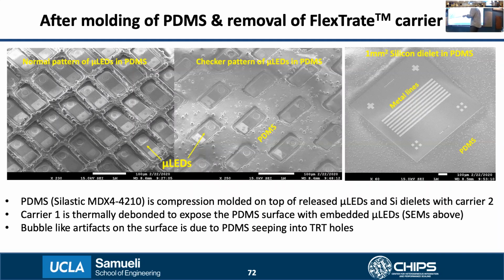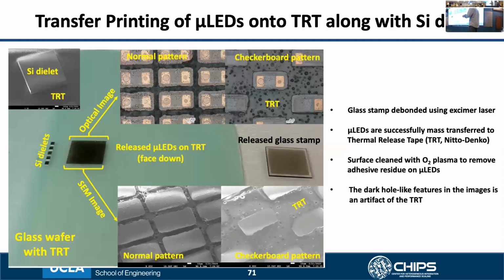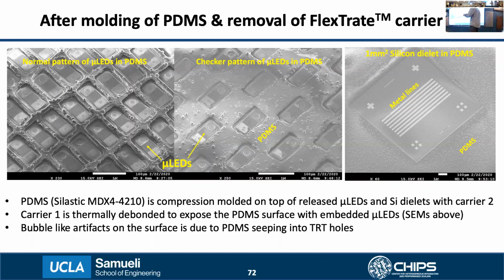So these bubble-like features that you see on the surface are actually an artifact of the thermal release tape, because the thermal release tape, if you notice here, has some roughness. And when we compression mold, the PDMS fills those holes, and those are the roughness that you see here.